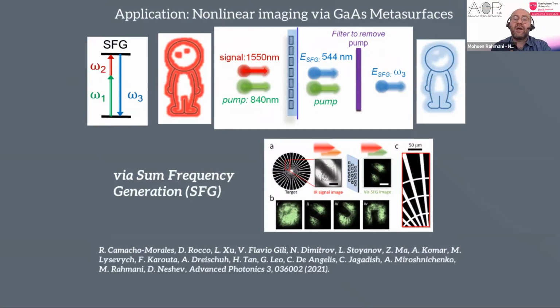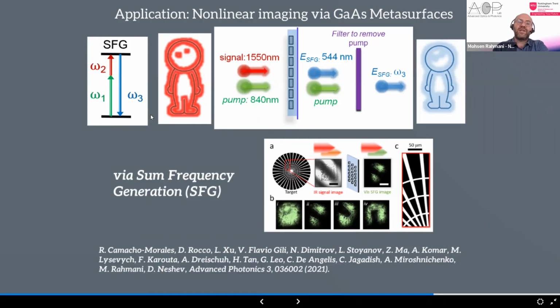And finally, because we get very good efficiency with III-V semiconductors, which was not possible with plasmonic nanostructures, because we were bottlenecked in terms of the efficiency, but with III-V semiconductors we got very good efficiencies. And then here we managed to show a very good application, which is nonlinear imaging by these nanoparticles. This paper was published last year. So we use sum frequency generation here.